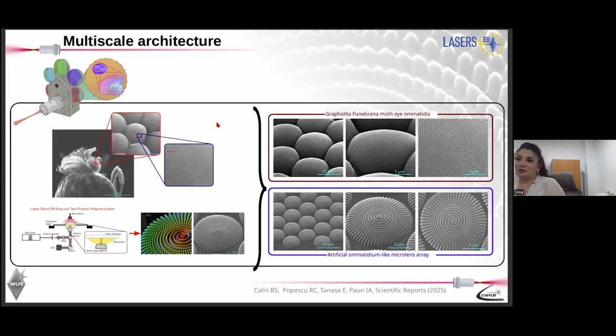I will quickly summarize our next approach. Using this idea of hierarchical structures, we looked again at examples from nature, and we found that nocturnal insects such as the Grapholita funebrana moth have eyes like this. They have ommatidia-like structures, which are hemispherical ones in the micrometer range, covered with nanopillars. These nanopillars have the role of decreasing the reflectivity in the infrared, so during the night, because these insects do not want to be detected by predators, and also of increasing the transmission in the infrared, because these insects need good vision in the infrared during the night.